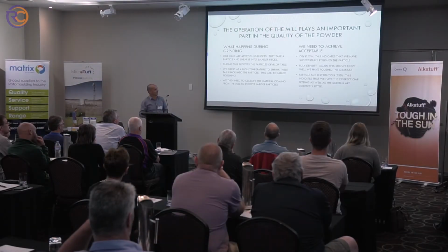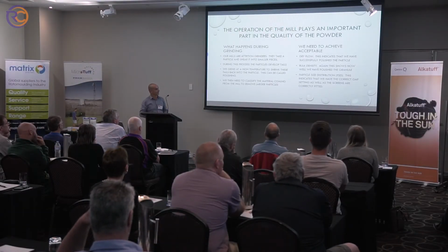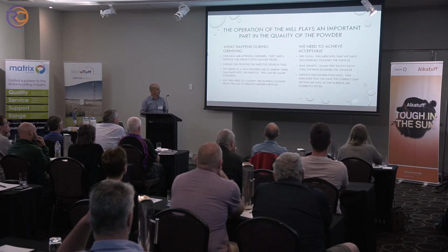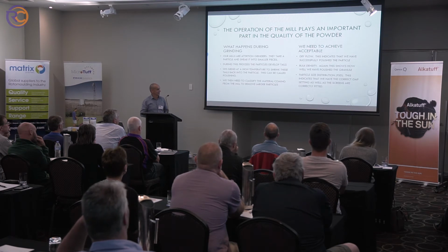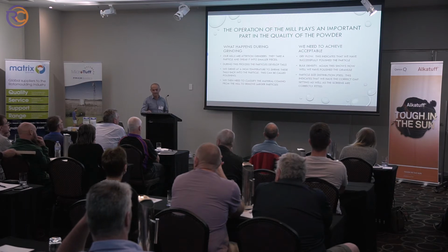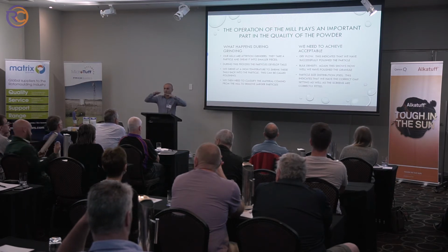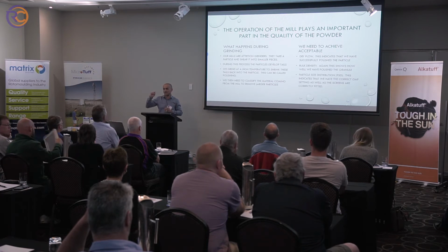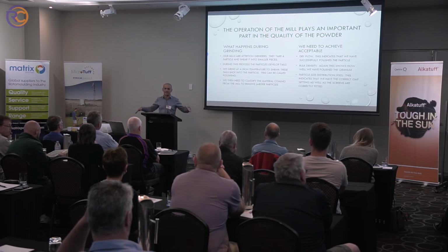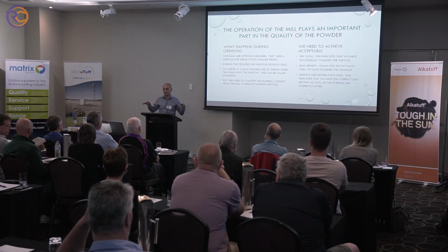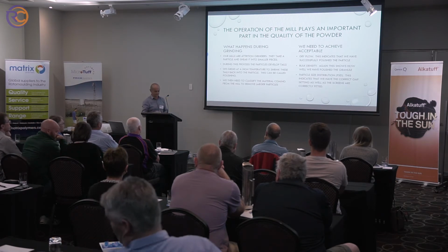The dry flow indicates that we have successfully polished those particles, and so does the bulk density, also shows that the particles are polished well. Particle size distribution is an indication of the correct gap setting, as well as the screens are correctly fitted. But when we're grinding powder, not everything's ground just to 500 or 600 micron. There is actually a distribution of particle size, and it's that correct distribution that gives you a nice surface finish, the correct fusing of the materials, and also helps with the dry flow properties.